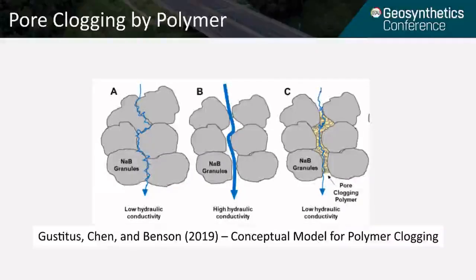While when you have high ionic strength or higher divalent cations in the leachate, you will see sodium bentonite granules that have a shrinking structure or a granular structure that leaves macropores for the flow to occur. The polymer BPC GCLs are obviously designed using the polymer to form hydrogels in between these pores and create low hydraulic conductivity under high ionic strength leachate, where the sodium bentonite is not swollen as you expected.